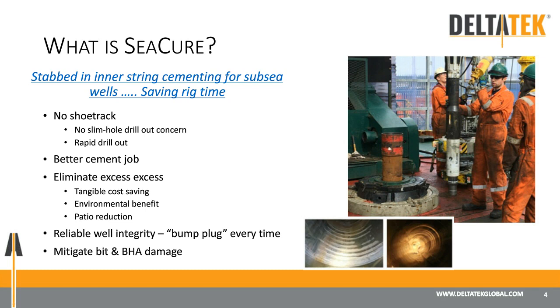On the bottom of this slide, you can see a cross-section of quite an interesting scenario which one of our clients brought to us in retrospect of some of the opportunities that they see as SeaCure bringing to their operations. This picture was taken from a recovered casing string which had a cement job not go perfectly well. In respect of the cement was inside the casing at the end of the cement job. So the operator drilled out the cement and then recovered the casing string.